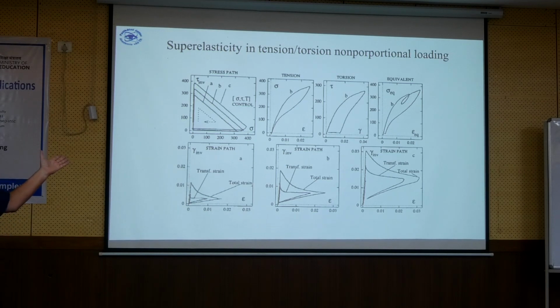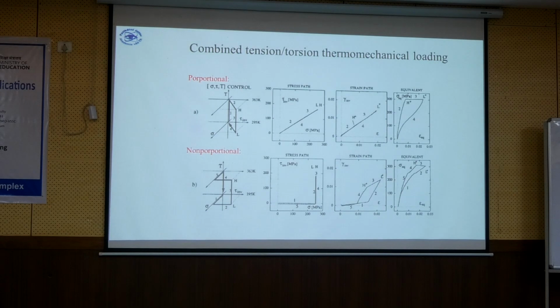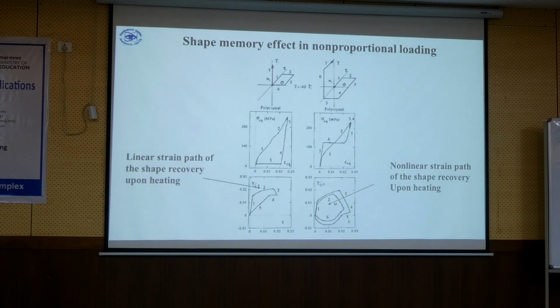So after that, we also made the experiments on nitinol, and the responses which we measure were quite different. Okay, so then we also did thermomechanical experiments. So here we have temperature also applied. The shape memory phenomena works very well. It's described in the article, and based on this, other people in the literature started to perform similar experiments on copper-based alloy, and the first general non-proportional SMA models were introduced by using the data of this. Also in France, some people did very nice experiments with the similar stuff.